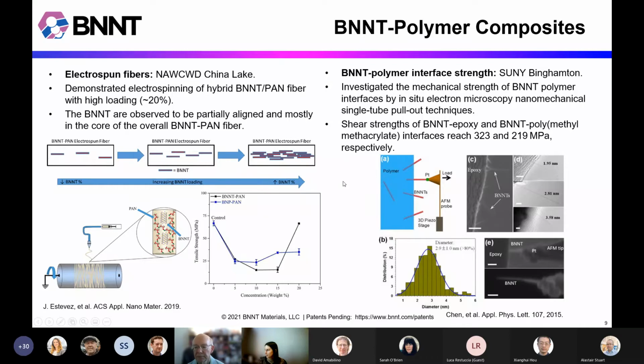Another example of some work with polymers is out of the State University of New York, Binghamton, Xianghui Hou. He's doing some more fundamental work to understand the interface strength of a boron nitride nanotube and a polymer. So he explored the shear strength of BNNTs in epoxy and PMMA by using a really neat method using an AFM probe and pulling out individual nanotubes and measuring the force that took. And they found that the BNNTs had really high shear strengths, and they attributed that to the van der Waals and Coulomb forces at the interface, and suggested that BNNTs are a great structural reinforcement, a nanofiller for polymer matrices.